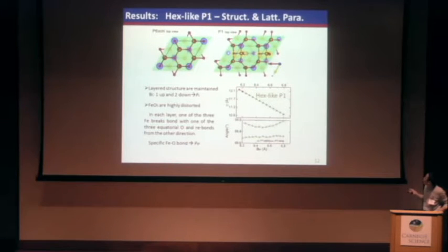And also we look at the lattice constant. For the out-of-plane lattice constant c, those two red dots are for the hexagonal structure, and the green ones are for the P1 phase. They are quite continuous. And since it is a thin film, we confine the gamma angle to be 120 degrees. And for alpha and beta angles, they are quite close to 90 degrees. So we call it the hexagon-like P1 phase to distinguish it from the perovskite P1 phase.